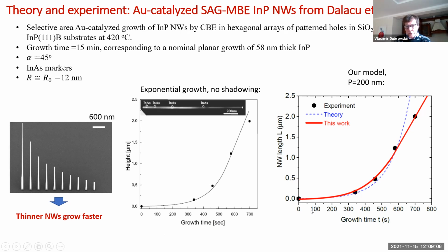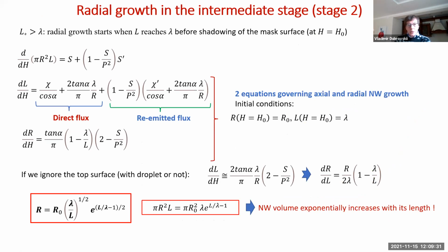So if we take into account the shadowing effect as well as reflection, the specular reflection in my case, the curve would fit the results much better. So there is no discrepancy at all, compared to the exponential curve, which was produced again without taking into account shadowing. Of course, in self-catalyzed nanowires we see radial extension all the time, in most cases. So we can't say that these nanowires grow at a constant diameter. We have to consider radial growth in the intermediate stage, which means before reaching the maximum flux, okay?